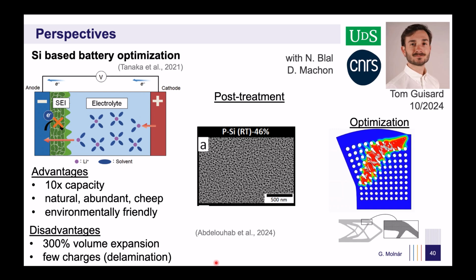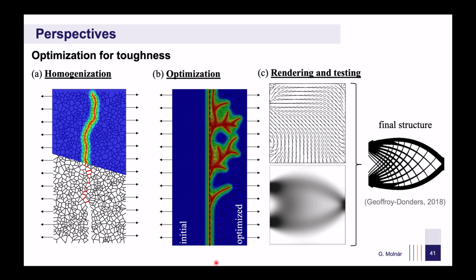However, the ultimate goal is to develop a universal design tool capable of optimizing the toughness of architected materials by effectively trapping crack branches. Achieving this would require developing a robust technique to homogenize the toughness of microstructures, using a continuum-based method to optimize the topology of the envisioned structures, and then finally translating these optimized designs into real beam lattice materials.